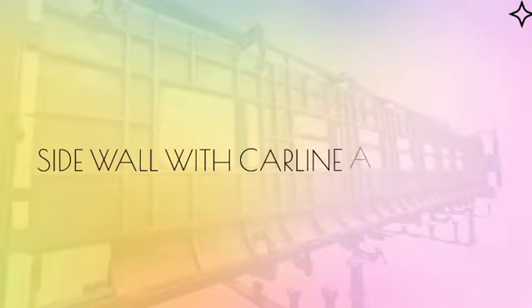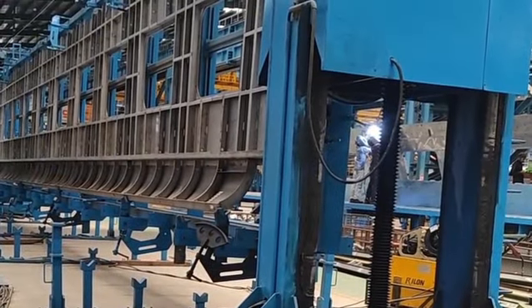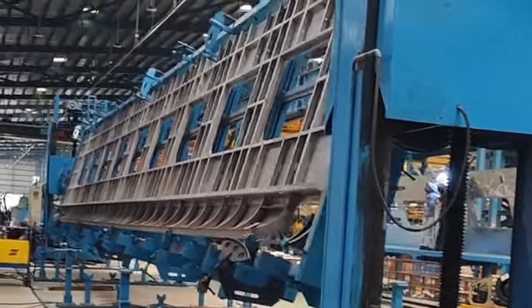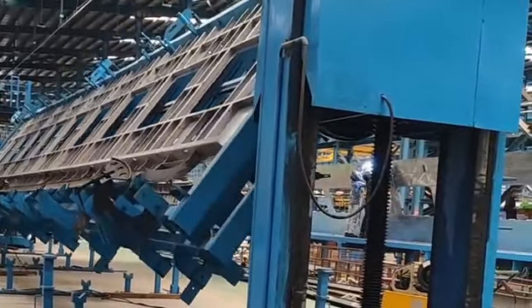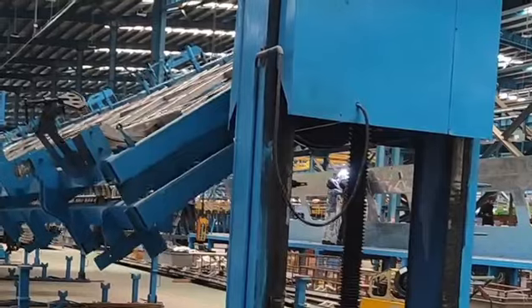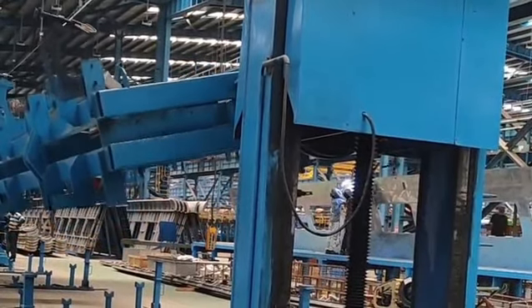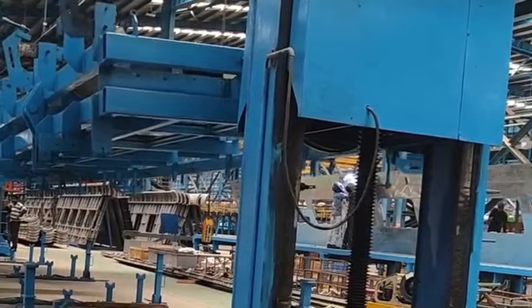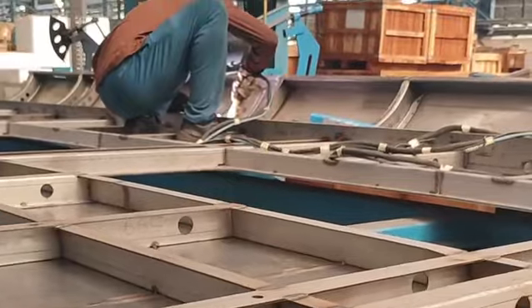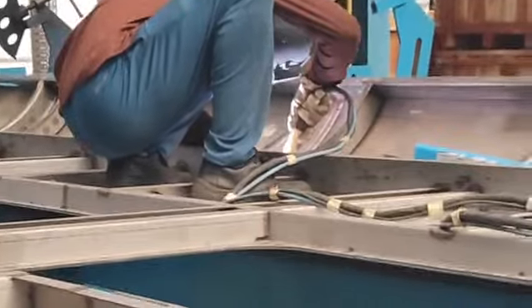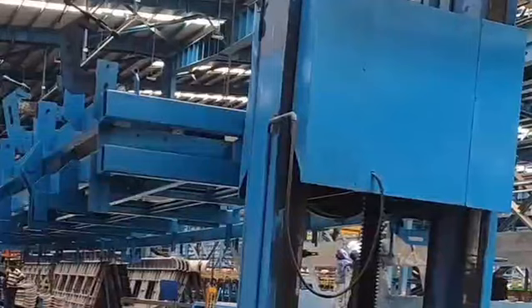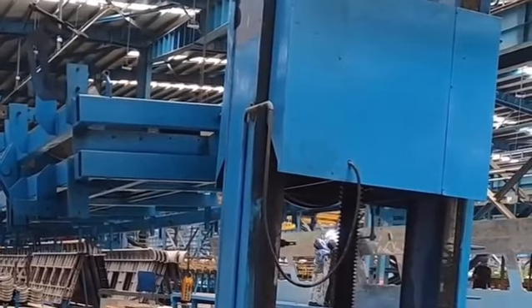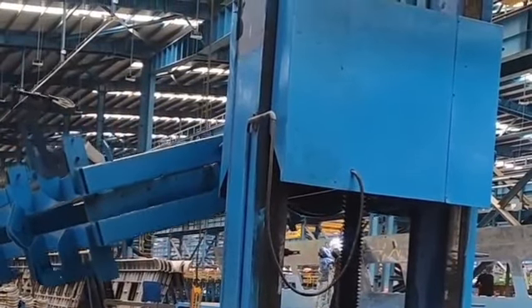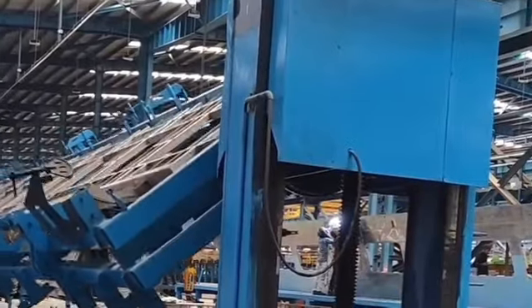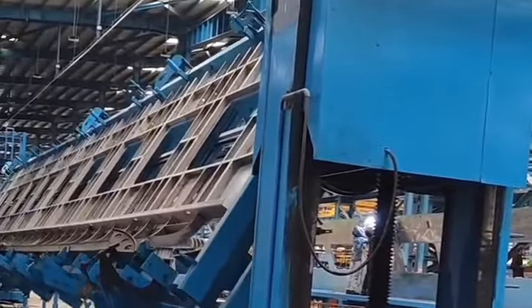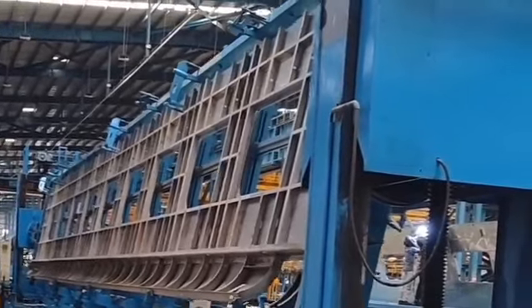Next stage is the car line with sidewall assembly stage. Once the sidewall assembly, that is the sheet and framework, are spot welded together, the car line and sidewall assembly are placed together in the car line sidewall assembly fixture, which is a rotating fixture. In this stage, first the fixture is kept in horizontal position where they are clamped properly, and after that tack welding is done. After ensuring the dimensions, full welding is carried out between the car line arches and roof flange of the sidewall. For both tack welding and full welding, tungsten inert gas welding is used. Once the car line is welded to the sidewall assembly, the fixture is rotated 90 degrees and comes to vertical position.